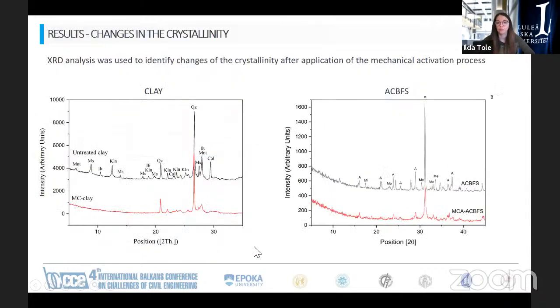Not only was the particle size distribution evaluated, but to evaluate whether we are getting amorphization of the crystalline structure, which for us is the main indicator of reactivity of the material, we did some X-ray diffraction analysis. And as you can see, for the clay, all the peaks of the phases that were found in the untreated material then completely disappeared after treatment. That is a sign of amorphization of the structure. The same thing was happening for the air-cooled blast furnace slag. So we have really amorphized material after treatment in the grinding machine.